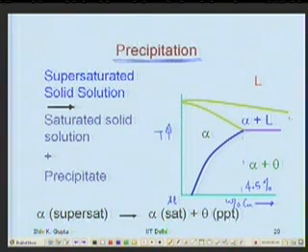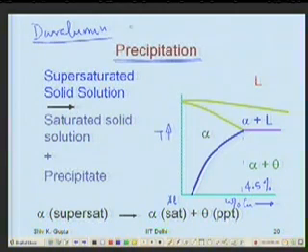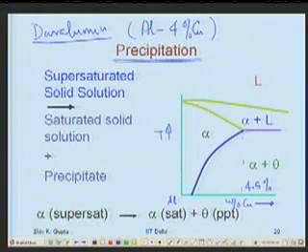The alloy which we use for discussion of the precipitation is duralumin. Duralumin contains aluminum and basically 4% copper. Usually there are some additions of titanium like 0.5%. We'll not worry about that because we look at the binary diagram. Well, let's say I take an alloy with 4% copper. I am somewhere here. This temperature is around 550 degrees centigrade.